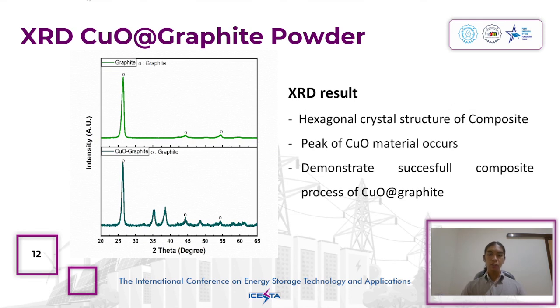The structure of the graphite was hexagonal. This is shown by the XRD analysis of copper oxide and graphite powder. The composite sample XRD curve pattern shows very high intensity for peaks associated with the graphite material. The result also shows peaks observed at the higher diffraction angle, indicating the presence of copper oxide components.